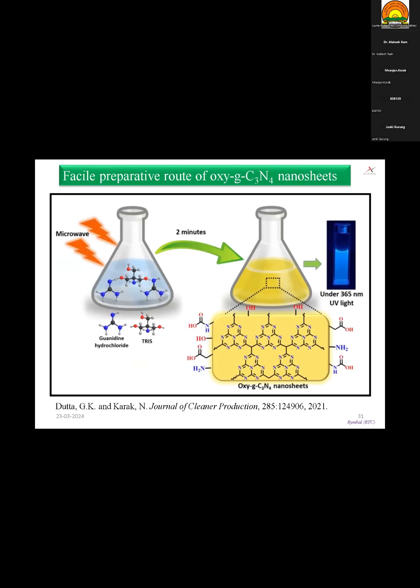On the other hand, zero-dimensional nanomaterial like oxygenated carbon nitride dot, or two-dimensional nanomaterial like oxygenated carbon nitride nanosheets, can also be obtained through a simple technique from guanidine hydrochloride by using an autoclave system or microwave energy, which can produce a highly photoluminescent nanomaterial.